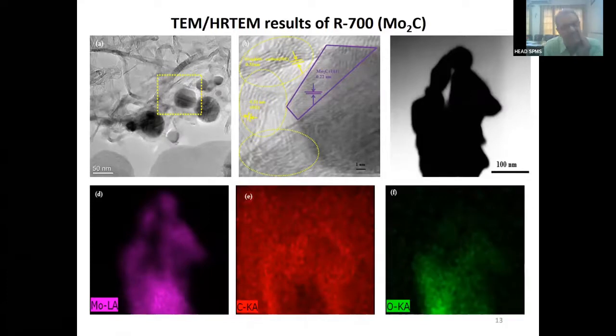As far as TEM, transmission electron microscopy, is concerned, you can see that the features are full of carbides along with some carbon substances in the form of either rod or graphene. And the second thing is that if you measure the spacing, you will find that this spacing confirms that the material is molybdenum carbide. We have taken different features where the presence of molybdenum, carbon, and even oxygen is important.